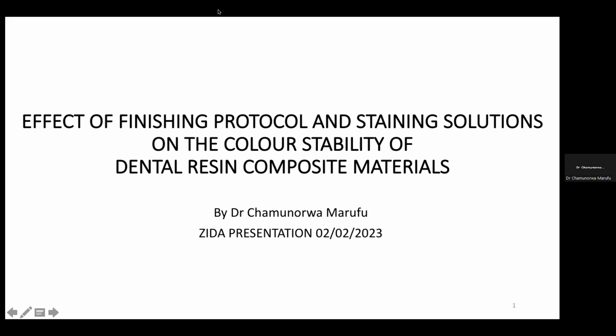So when you have a situation where there is more resin in composite, it's most likely expected that the restoration will discolor more. I'm sure you have noted that nano composite was more color stable compared to the micro hybrid when it finished in Mylar. And as I said earlier, the nano composite had 63.3% volume of the fillers compared to the micro hybrid, which is like 55% thereabout.